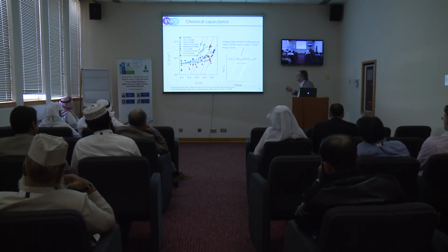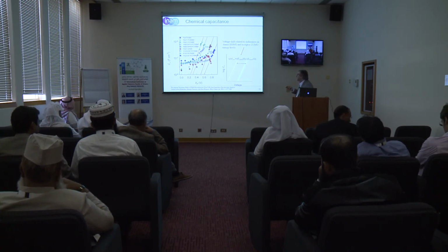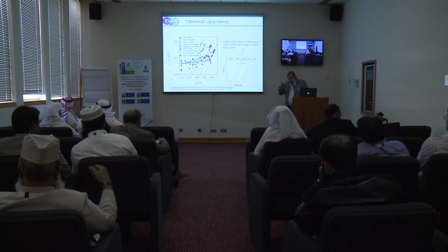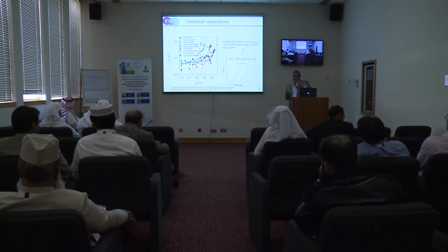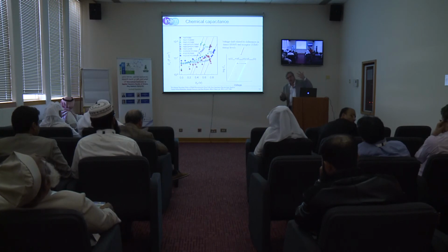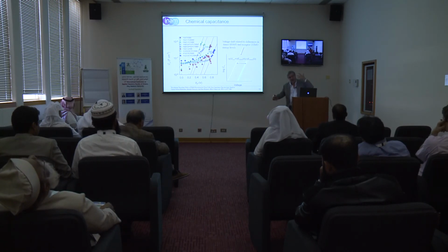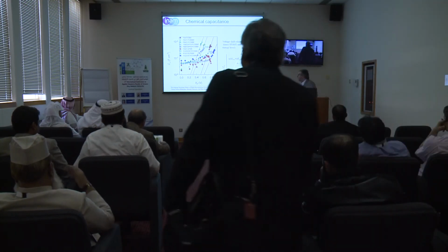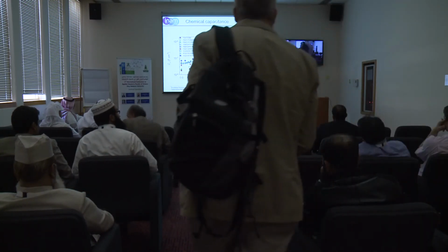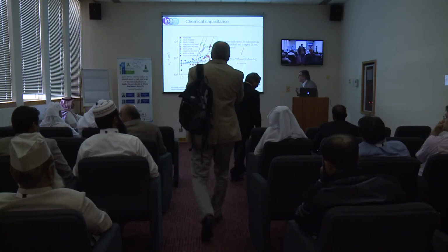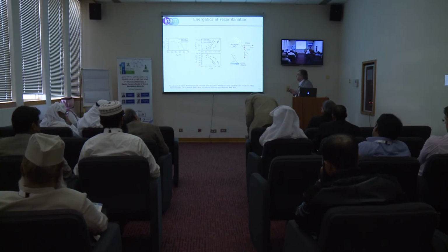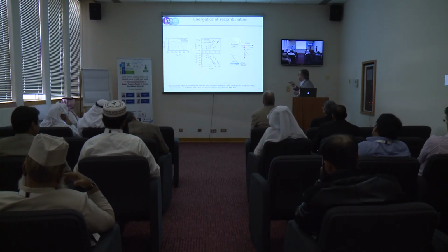Of course, this PCDTBT with the fullerene C70 is giving the higher voltage, because again it has the highest difference of the energetics of electrons with respect to the electronic polymer. So this is the most efficient solar cell, and we can see that in part this is because it has the best energetics. But it's not only energetics.